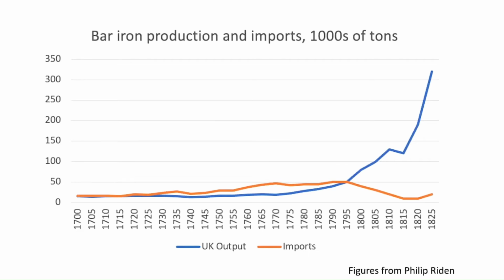There was one more development, which I haven't really majored on because it wasn't 18th century. It's not immediately obvious. I mean, various people have been cited as being responsible for the novelty. But I think it was one of those things that just sort of happened because people started using slag and iron oxide to protect the bottom of their furnace. And they discovered when they did this that if you put enough in, and it was rich in iron oxide, then you could pour high silicon iron straight from the blast furnace into the puddling process. And the iron oxide would react with the carbon at the bottom of the bath, react with the silicon as well.